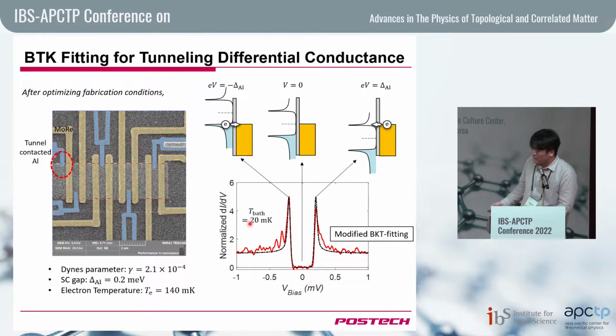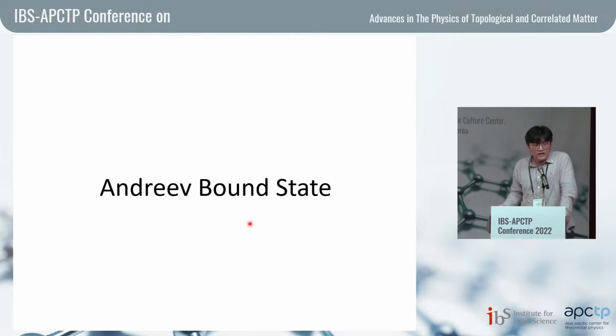And that material has a flat density of states. If we fit it with BCS theory, we get reasonable numbers for the superconducting gap and electron temperature. Moreover, the Dynes parameter, where smaller is better, since it means a longer quasiparticle lifetime in the superconductor, is small, which means good. And we can see this sharp density of states peak, which is good. So this is our method to see the density of states of some material, and I will talk about what material, what kind of system we want to look at.